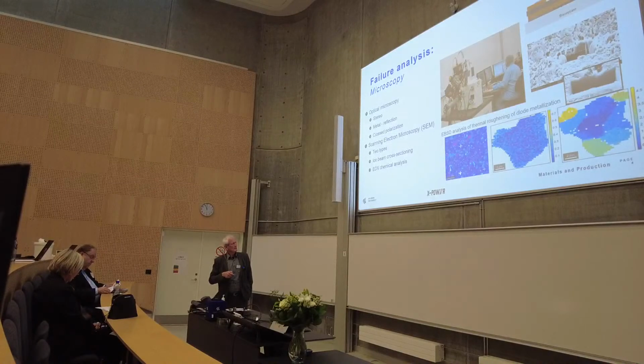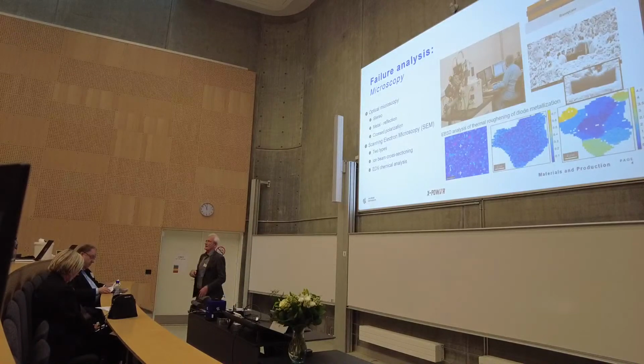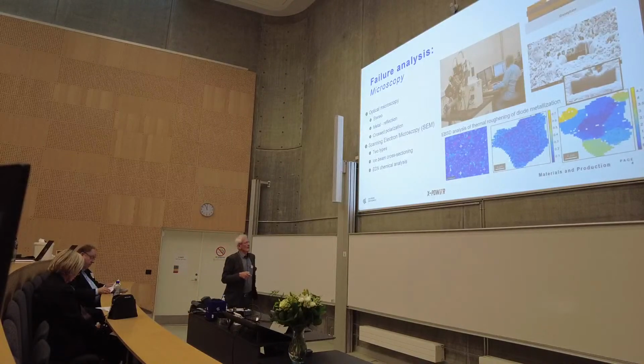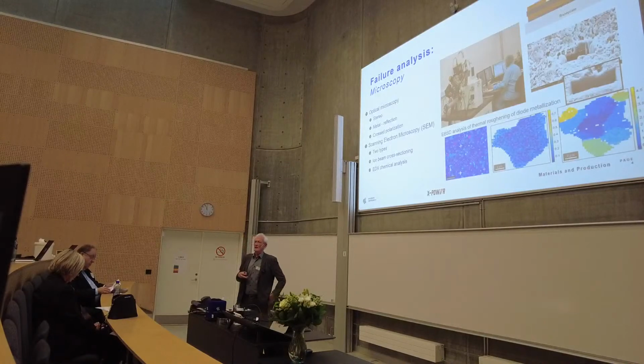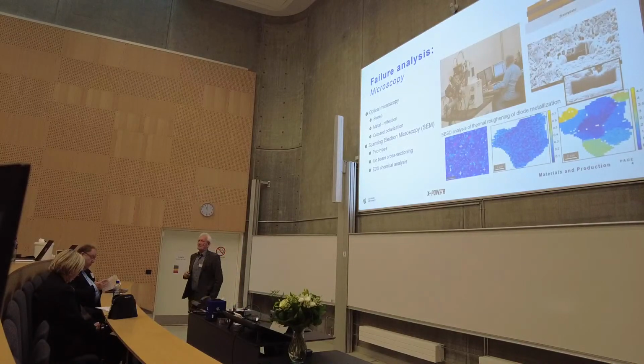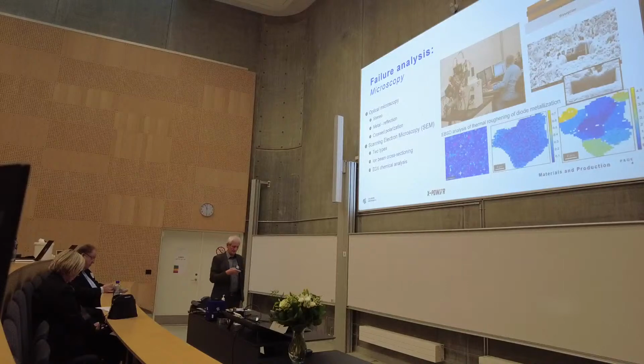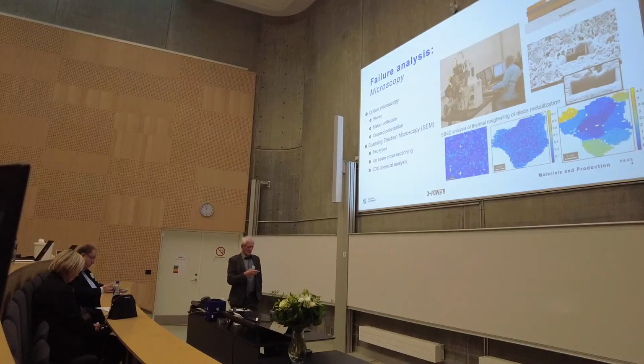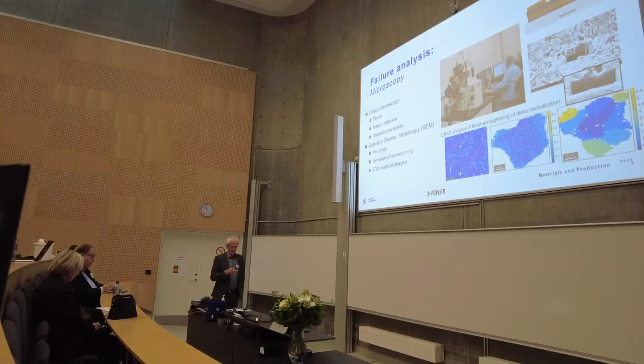We have made some marks, which means that we could take the sample out. We can do new cyclings, go back and look at the same grain, try to find it because we have made some marks on it. And eventually you can see that the grain splits up in more and more grains. And this is what gives you this very rough surface that eventually makes the bonds that are made to this break. So these are the opportunities you get when you start to look at it with electrons.